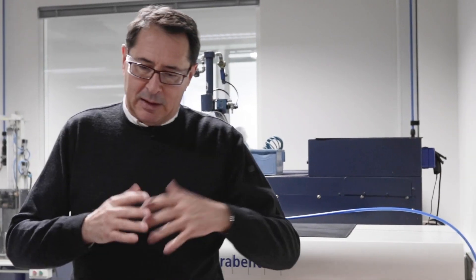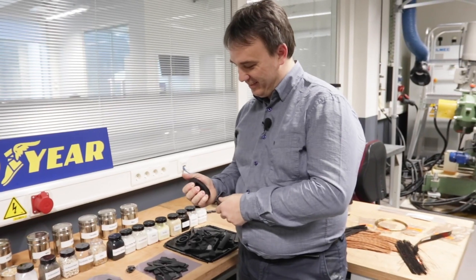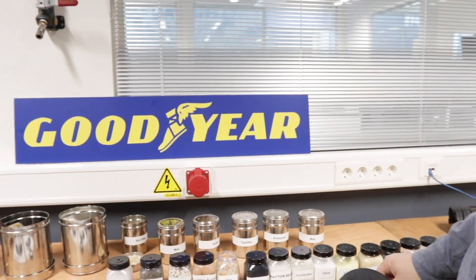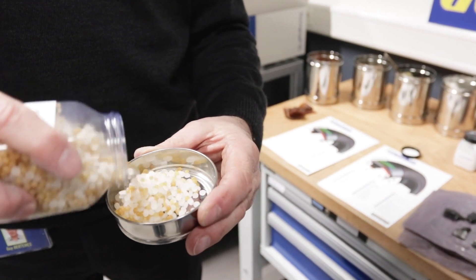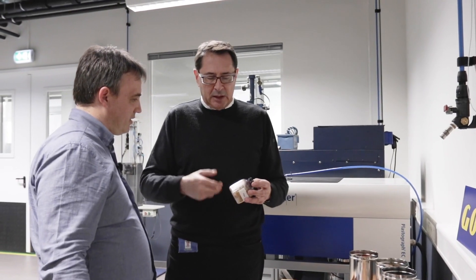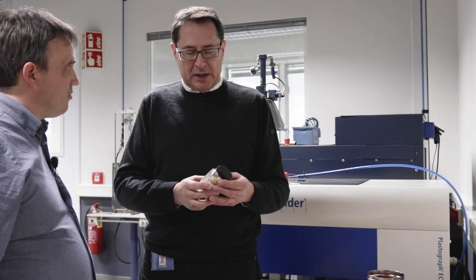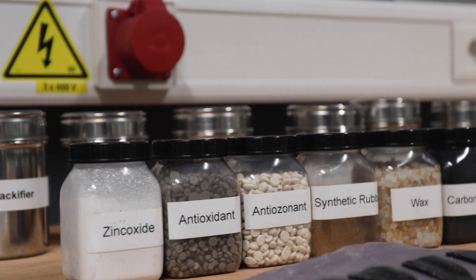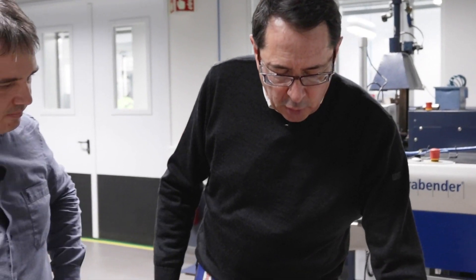That's the whole magic of producing compound — vulcanizing — and the tire is ready. This is a small sample; we have other mixtures for summer tires and for winter tires. We also have additives like antioxidants to protect your tire against ozone, sunlight, and everything on the road — otherwise your tire would be damaged rather fast. We also have accelerators, retarders, and tackifying resins.